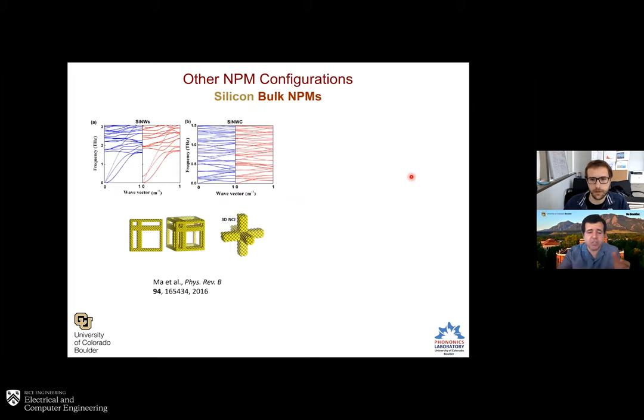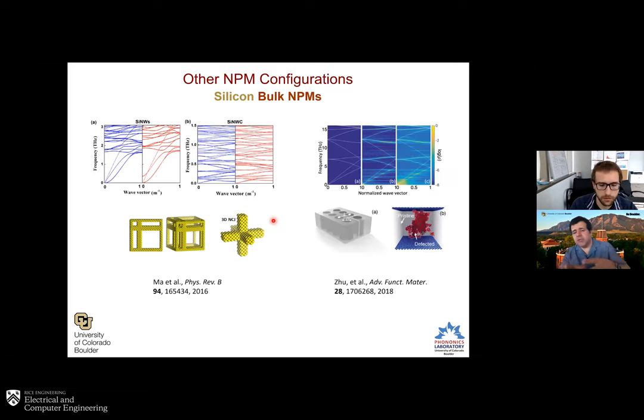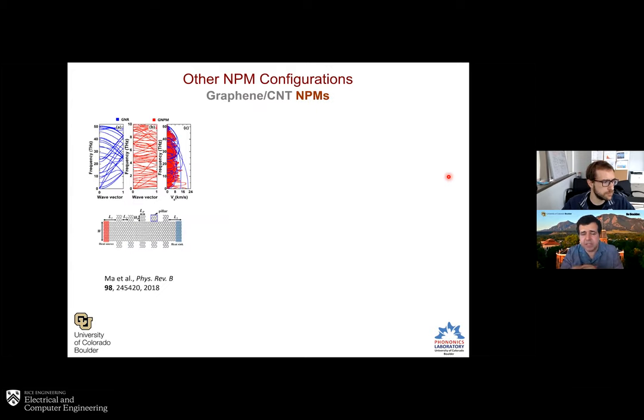Also at the bulk scale. This group examined a bulk system whereby you have these networks, and these networks act as resonators. And once again, you can see the resonances and their couplings, and they've shown also that this reduces the thermal conductivity. And from Illinois, they've shown that if you introduce a resonator in the form of amorphous silicon, there are resonances among the amorphous region, which itself also produced the same phenomena and gave you these hybridizations, or at least these local resonances. In fact, even other types of materials like graphene and carbon nanotubes.